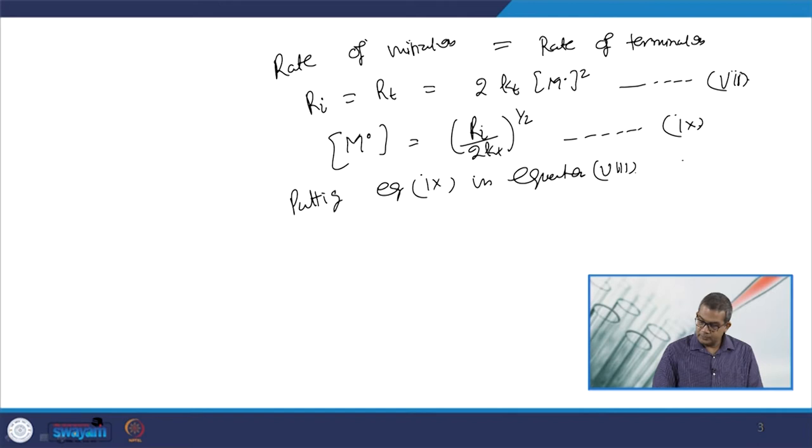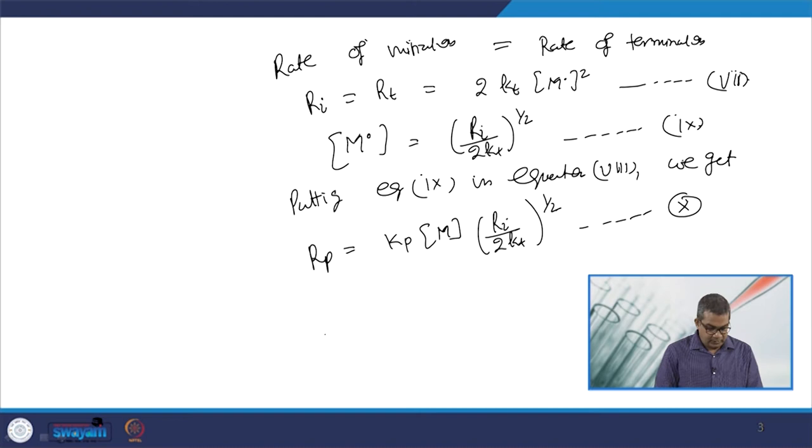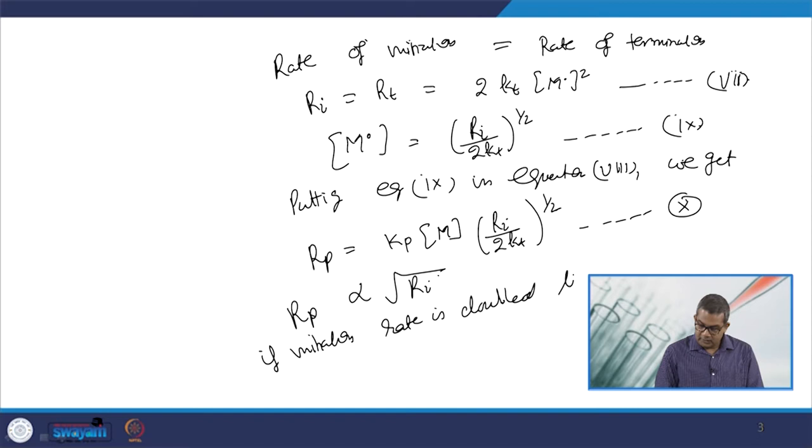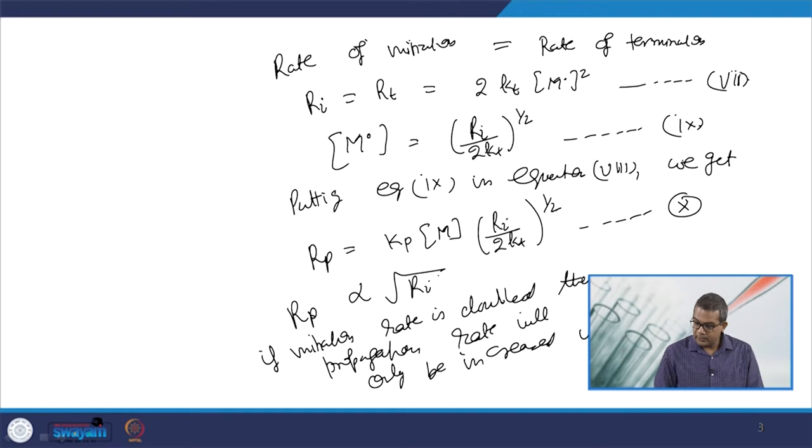So we get Rp is equal to Kp... this is equation number 10. Now from this equation we can conclude that our rate of propagation reaction is proportional to rate of initiation. So if initiation rate is doubled, then propagation rate will only be increased with the factor of,